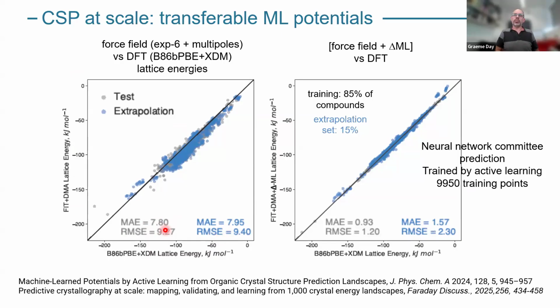Okay, so we want to not rely on cancellation of error so much, and that means that we'll be more confident in applying the method to new or more unusual molecules. So after training on this set of now about 9,000, 10,000 training points, here's the correlation we get. We're getting errors down to about a kilojoule per mole, and that's on the crystal structures of molecules the training has seen in gray. And in blue here, it's crystal structures of molecules that are completely unseen to the training of the machine learned model. We're still getting accuracies down to about 1.5, 2 kilojoules per mole. So that's really quite good. So we have a generalized machine learned model which lets us correct force field based quick energy evaluations.